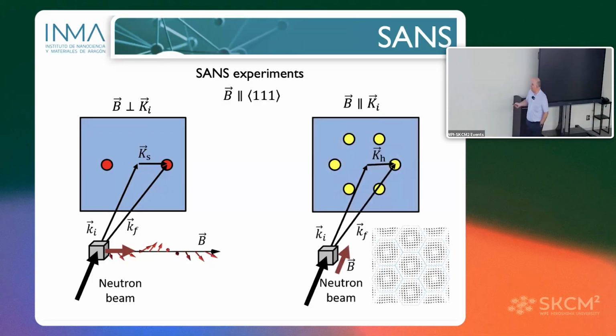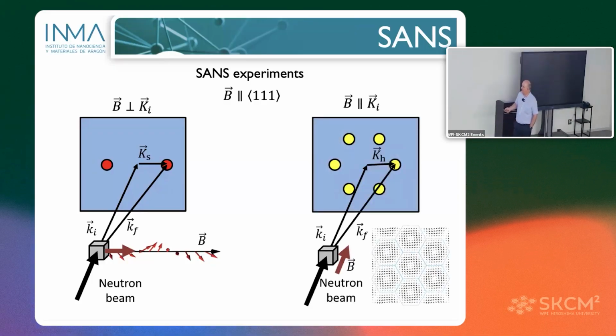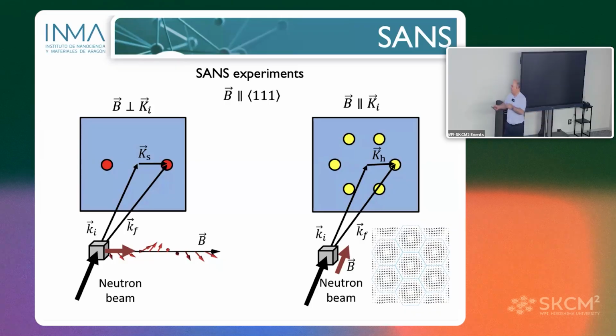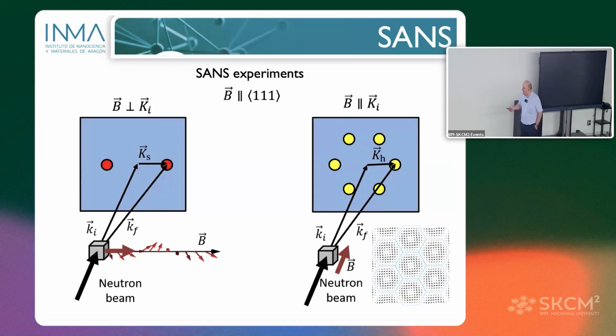If you want to observe a skyrmion lattice, you need to put the chiral axis, or in this case the axis perpendicular to the screen, parallel to the incoming neutron beam. And you need a magnetic field to form skyrmions. You need a magnetic field parallel to the, in this case, perpendicular to the screen, and you need to apply it parallel to the incoming neutron beam.